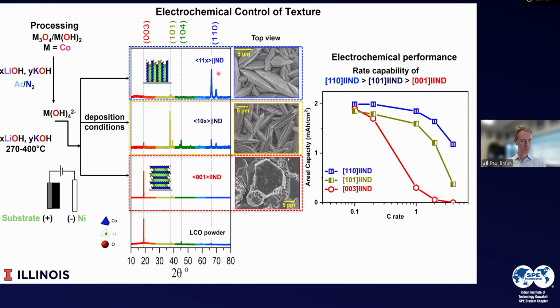Because we do this electrochemically, we have additional knobs. Unlike, say, a high temperature process, we are able to vary temperature. We're able to vary the concentration and chemistry of the precursors. And what that allows us to do is control crystallography. So we can grow material so that it's highly oriented in the vertical direction, or highly oriented horizontal, or parallel to the substrate.